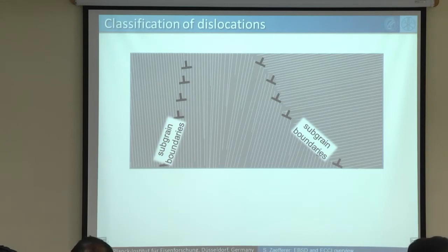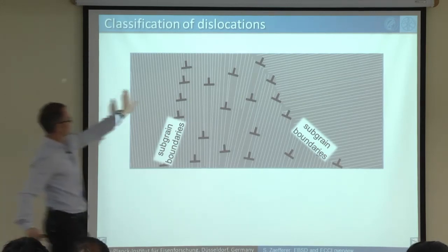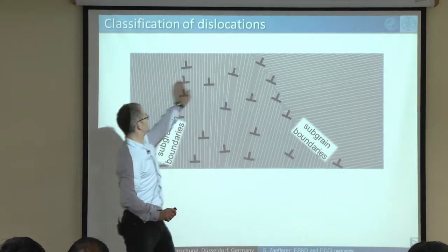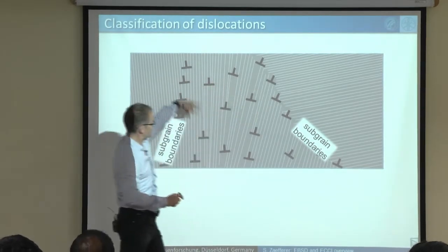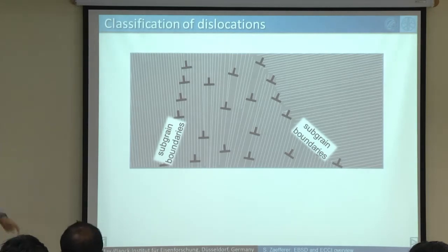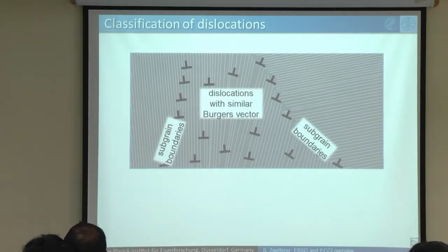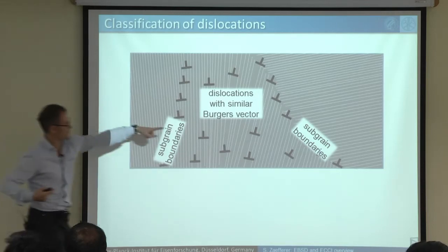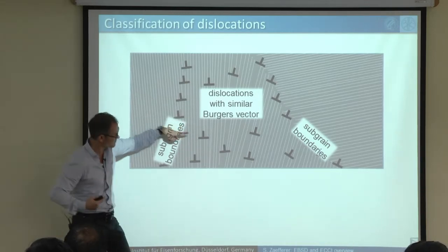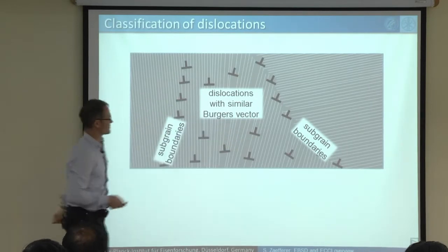And then we have another set of dislocations. You see them here. I have plotted them, but just as ending lattice planes here. They are also more or less the same type of dislocations. They just make a rotation of the lattice from here to here. So the lattice slowly moves over from there to there by regular insertion of dislocations. So these dislocations all have the same Burgers vector. They all have a Burgers vector which is pointing this way. Slightly inclined, but in principle all the same thing with respect to the lattice.